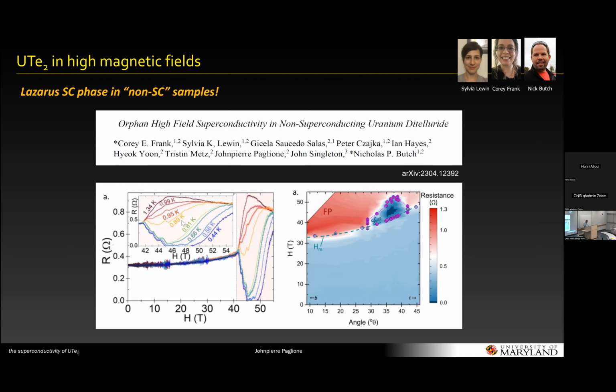Yeah, you can see here it's something like 1 Kelvin. So it's lower. And in fact, there's not much data about the temperature dependence of it. And this is only seen in transport, but not in magnetization? No, it's seen in transport, in TDO type experiments, and also magnetostriction. So there's Los Alamos work. There's thermodynamic evidence for this superconductivity. Yeah, so they claim the magnetostriction is consistent with a superconducting response.